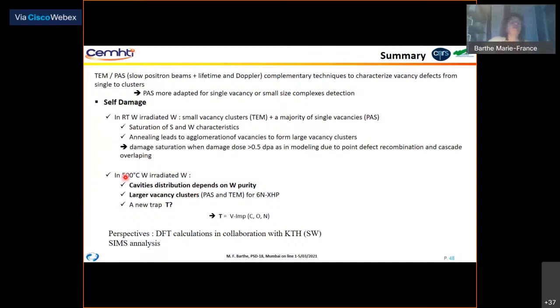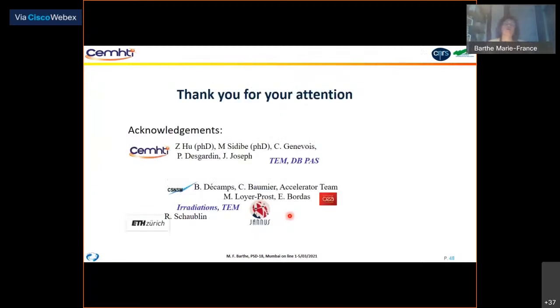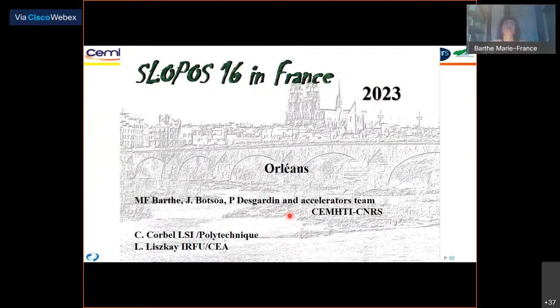And in irradiation at 500 degrees C, we have seen, in two different purities, that the cavity distribution depends on the tungsten purity. And we think that we found a new trap which should correspond to the complex between a single vacancy and impurities such as carbon, oxygen, and nitrogen. I thank my collaborators and, of course, you for your kind attention. Just to remind you, SLOPOS 16 in France in 2023.